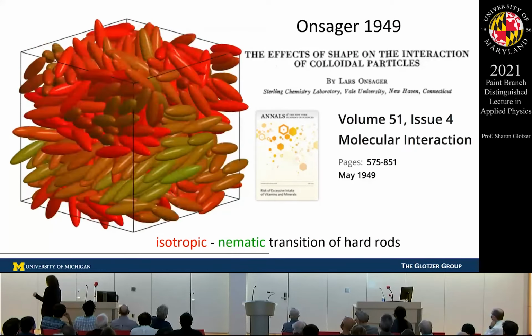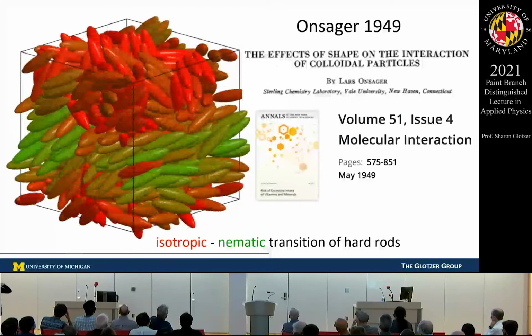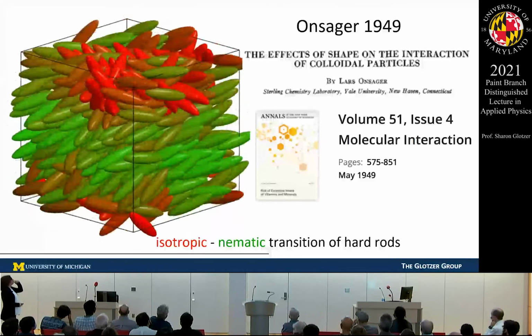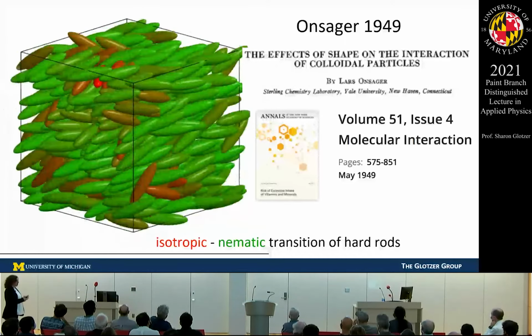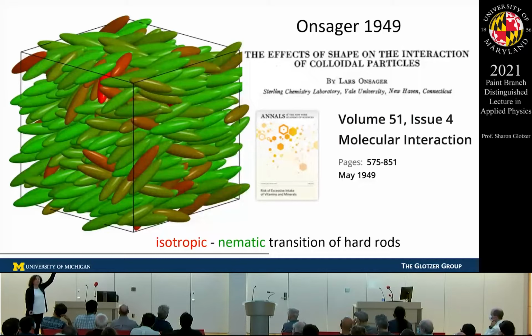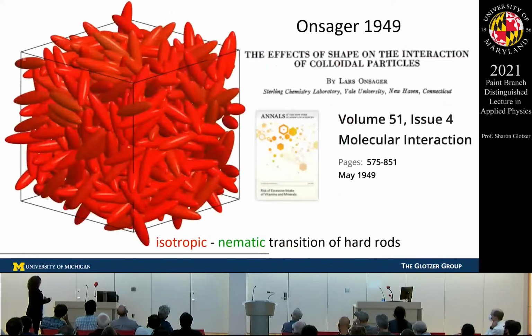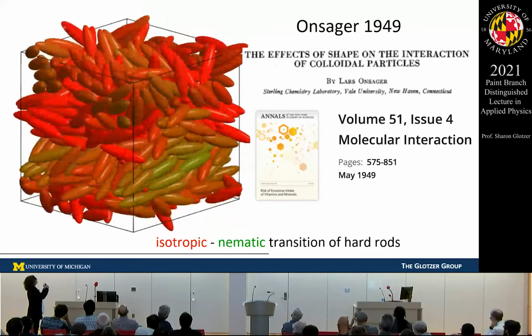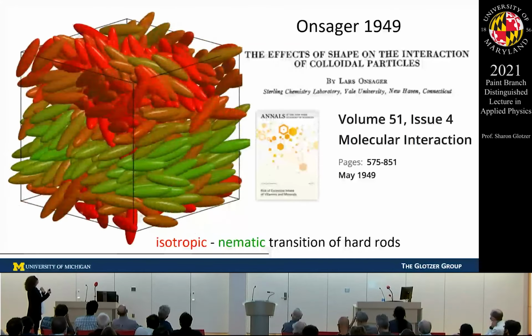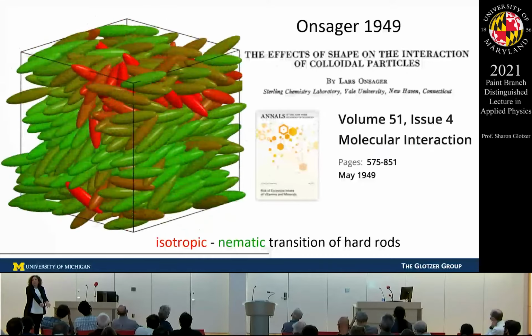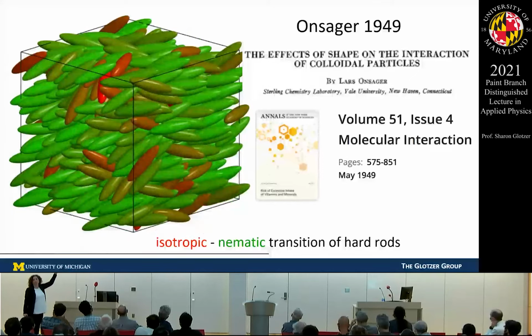It turns out that we have known that entropy can order systems for a very long time. Since the time of Onsager in 1949, Onsager said if you take infinitely long, infinitely thin rods and pack them together and keep increasing the packing fraction, at some point they're going to have to line up. They will give up rotational degrees of freedom to gain translational degrees of freedom in order to maximize the entropy in the system. And in this simulation, they're not infinitely long, but they are hard particles with an aspect ratio of about 5:1, and we color them green as soon as they start to align with one another. There's no interaction between these particles, and the system goes from an isotropic phase to a nematic phase.